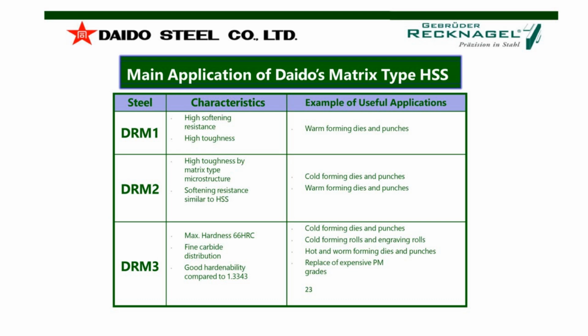And if you need a higher hardness of 66 HRC, DRM3 will be the right choice. You can use the highest hardness, and also a very high toughness and pressure resistance. And I can tell you from my experience with DRM3, I have a lot of customers who were using in the past some powder steel grades like Böhler K390, Böhler S390, or Vanadis from Uddeholm, Vanadis 4, 8, or 10, or from Erasteel.